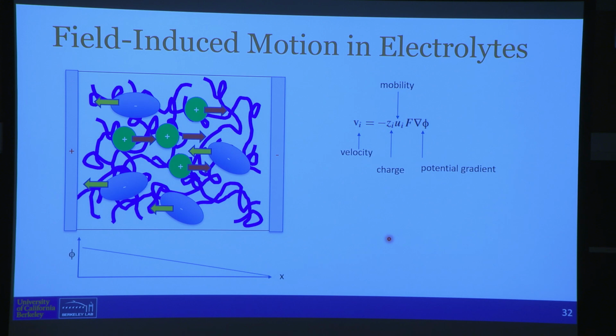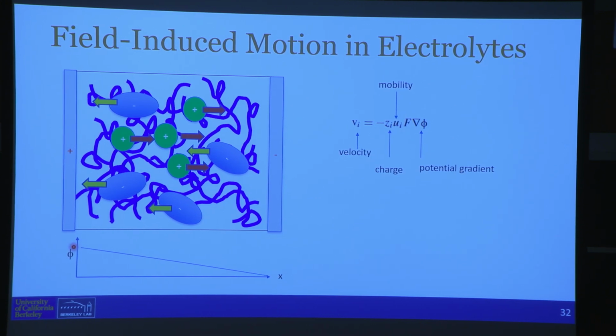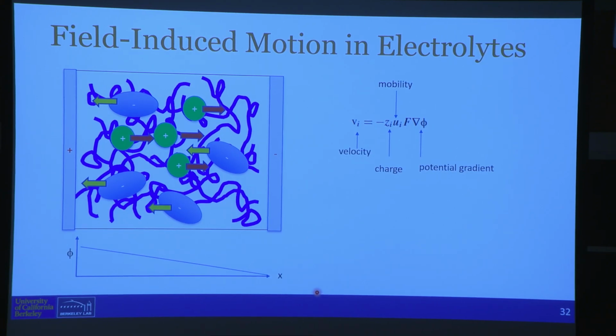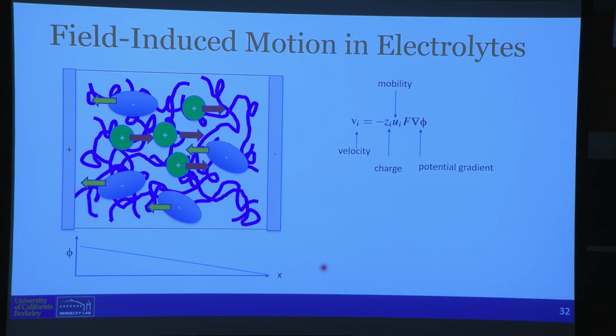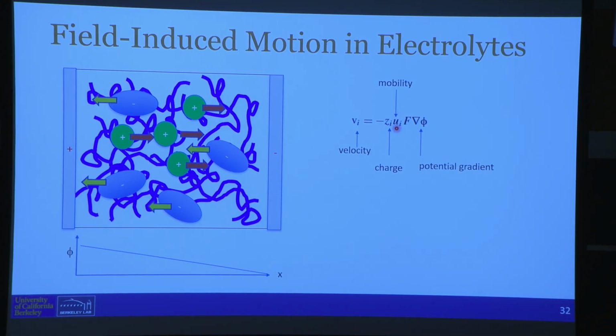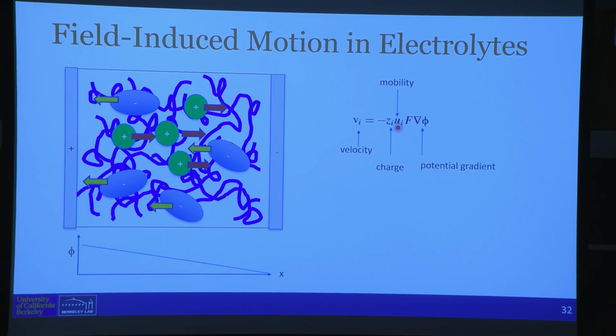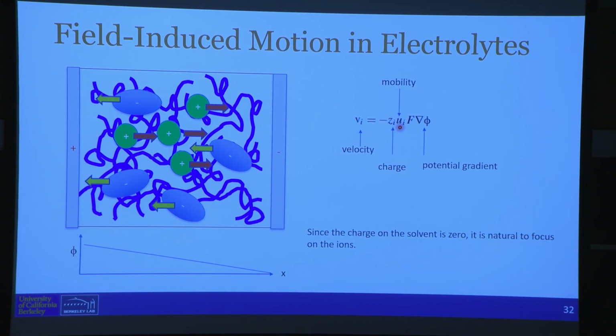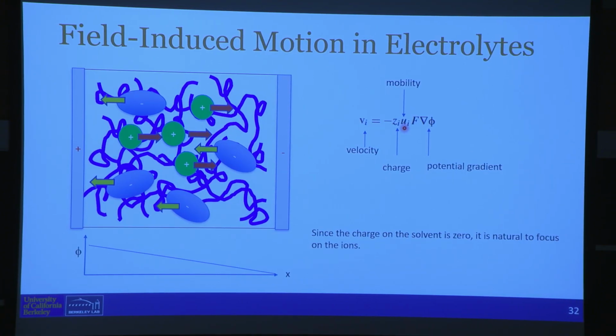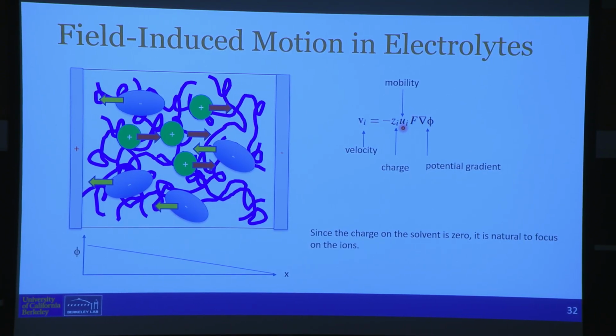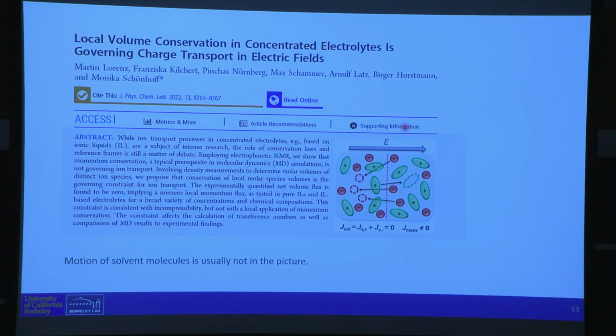So here's my battery again. Electrodes, now I'm showing a potential that sort of goes from some value that I measure to 0, and when you don't know how something goes, you draw a straight line. Okay? And in this straight line, the gradient of the straight line matters. That drives any ion with a charge of Z and a mobility of U, and Faraday's constant gets you the correct units. And obviously, if your charge is 0, then you'll get 0 using this formula, which is why neglecting neutral solvents is really steeped in the literature on electrochemical systems.